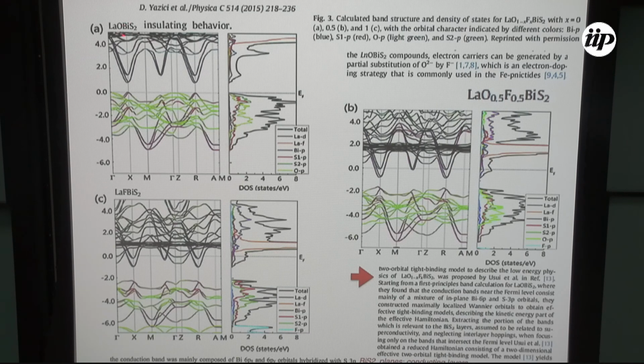If you change oxygen by fluorine, you obtain a metal. And the compound which has the highest Tc found in this family is actually when you dope half of the oxygen with 50% fluorine. And there you obtain this kind of bands crossing the Fermi level.